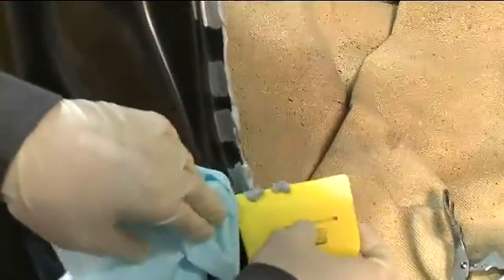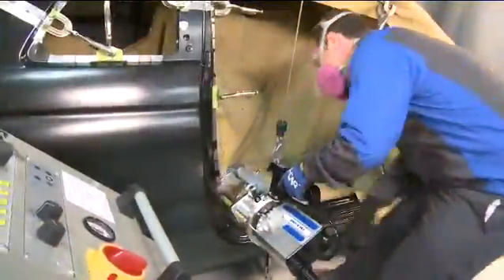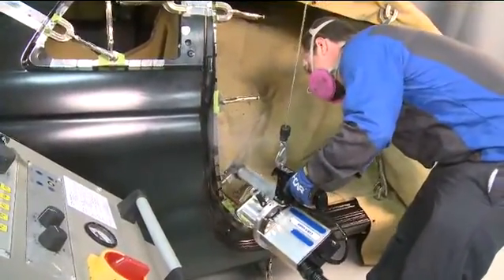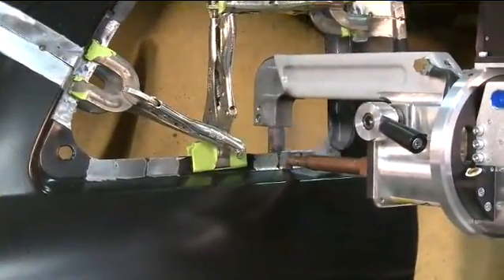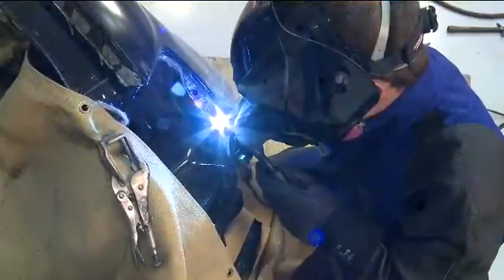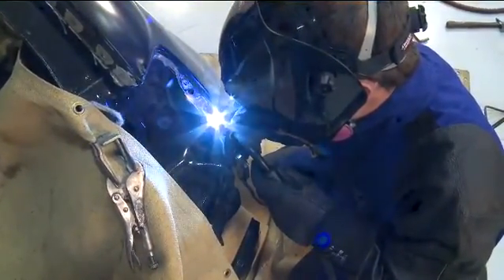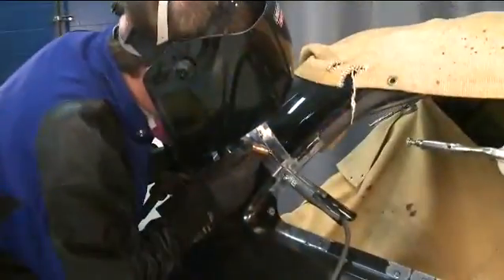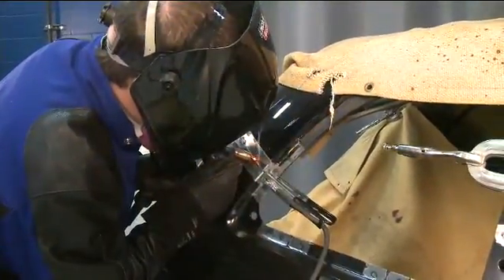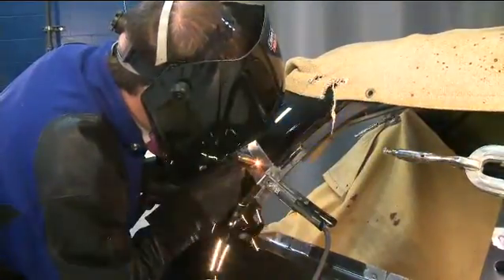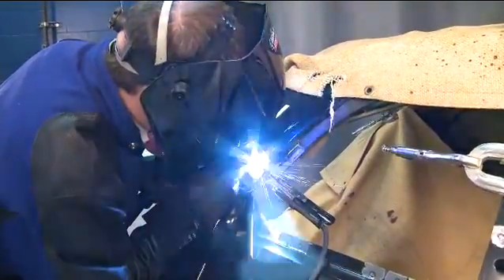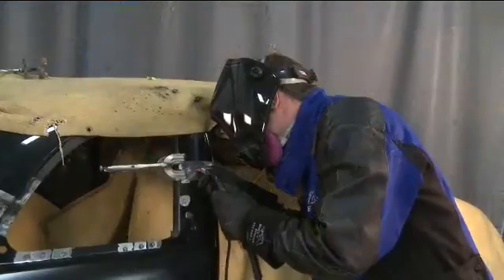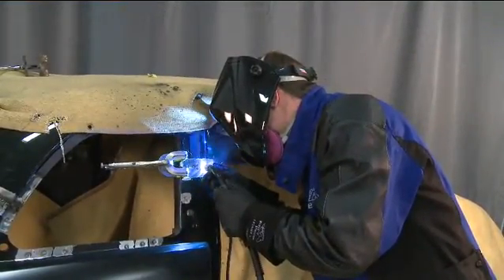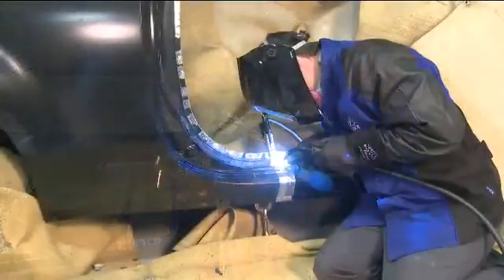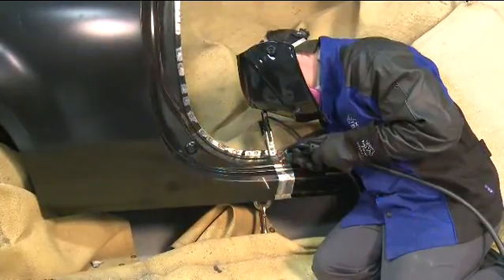Then, all squeeze out is removed from the bond areas, and spot welds are made prior to the adhesive curing. After the adhesive cures, all of the MIG plug welds are made. Now, the butt weld with backing is made at the C-pillar sectioning joint, using the skip stitch technique to avoid warping the panel. The same is done at the B-pillar sectioning location and the rocker sectioning location.